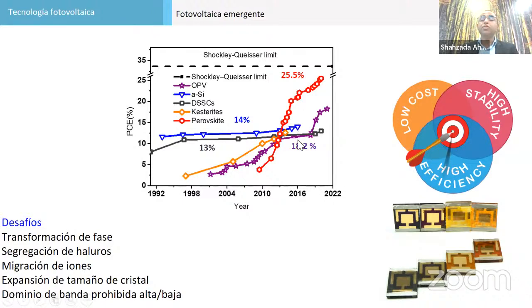Organic solar cells have also shown great performance in the last couple of years. Now almost 19% to 20% efficiency is being measured here. Amorphous silicon is flat at 14%. And if you look at other technology, DSSC has also not shown much improvement in the last 10 years. If you look at silicon, there is no improvement in terms of efficiency. The cost has gone down, but if you look at the efficiency chart, it is relatively small. The yellow-orange color is Kesterites, at 12.6%.